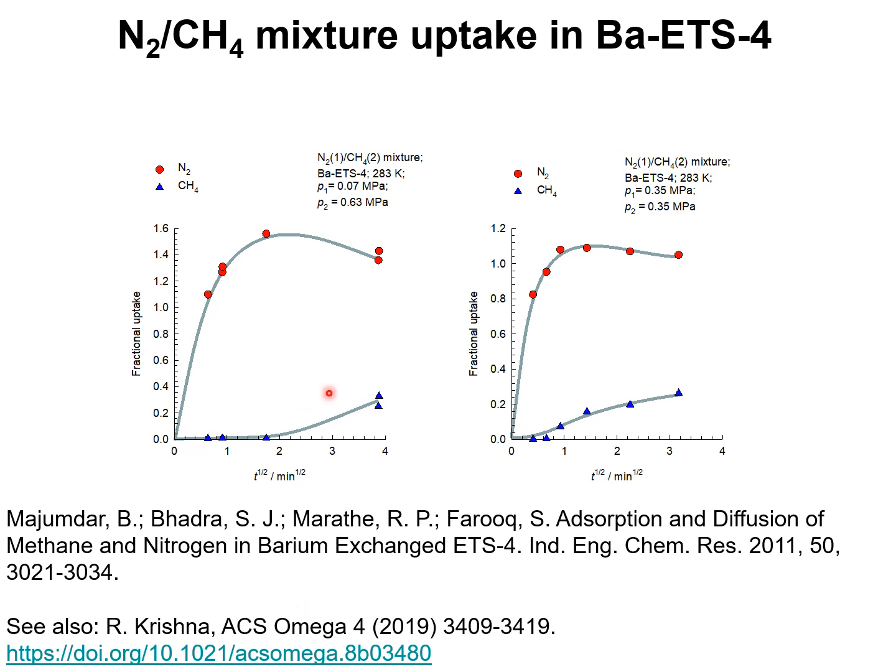They present two sets of experiments with two different compositions, both at a temperature of 283 Kelvin. The transient uptake data is remarkable in that the uptake of nitrogen shows a distinct overshoot in the loadings within the adsorbent Ba-ETS-4.